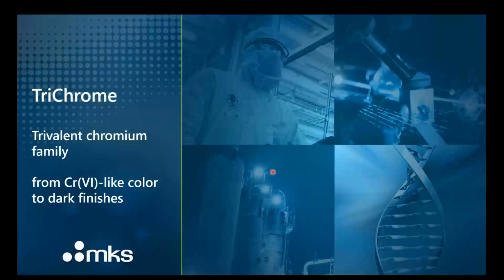But of course, here we are talking about the replacement of the hexavalent chromium, the chrome 6, from a plating on plastic line. And until now, we have discussed and introduced what happens in the pre-plating of this part. But also, if we want to eliminate the hexavalent chromium, we need to consider the end of the plating process, that is, when we plate the decorative chrome. And here the target again is to eliminate this chrome 6 from the decorative process. And for that, what we get is the trivalent chromium process.